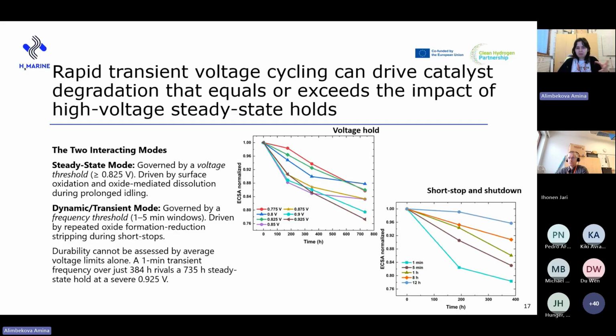The most critical engineering takeaway from comparing these two modes is that while it's important to identify the safe voltage limit, it's probably not sufficient to avoid or reduce the electrochemical surface area loss, because the repeated and rapid voltage transients are also significant.